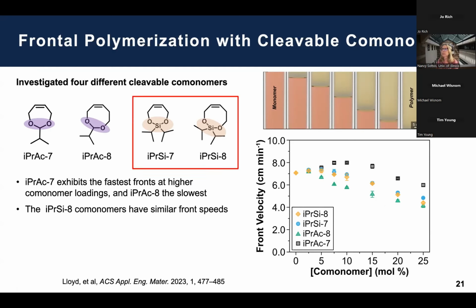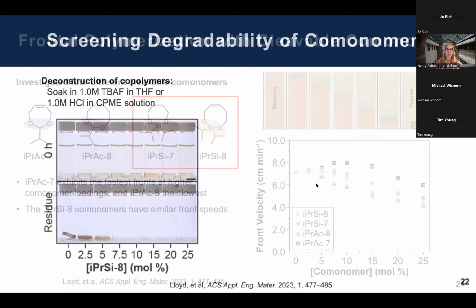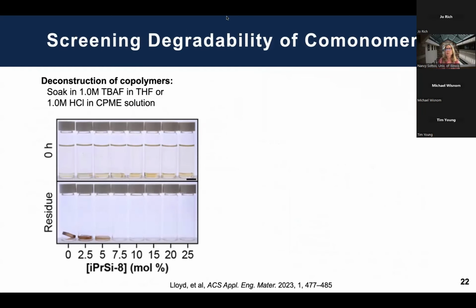It turns out that these 7- and 8-member silyl ethers incorporate best into the network and actually are the most efficient at deconstruction. Let me show you a little bit about the deconstruction process. These are just little scint vials with pure polymer in them. This has been frontally polymerized, at 0 hours. And you can see there's different amounts of the cleavable comonomer in here. So 0%, you would expect no deconstruction because that's a permanent network.